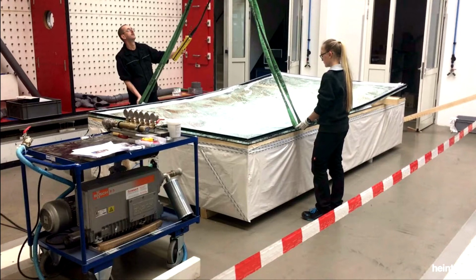And then also on that chamber, there was typical structural loading. So design and 2 times design, pressure and suction were tested. The deflections measured, everything checked out with what the models showed, about 6 millimeters of deflection under design wind suction. But we wanted to understand the ultimate strength and test 5 lights to breakage. The load to do that was greater than could be handled by the chamber. So CLA created this vacuum box in their factory. The light was sealed to it, and air pulled on it.